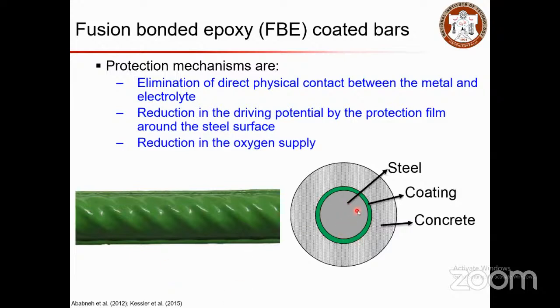You can see here, this is your steel rebar, then you have a coating, and then you have your concrete. In this case, the protection mechanism is that first of all you have concrete as your cover to protect your rebar. In addition to that, you have a coating. So even if something comes in through your concrete, the coating is there, protecting your rebar from the external source. For example, if this coating is not there, or if there is a hole or any path through which the aggressive agent can get in and reach your steel, that's where the problem comes, right? We'll address those things in the coming slides.